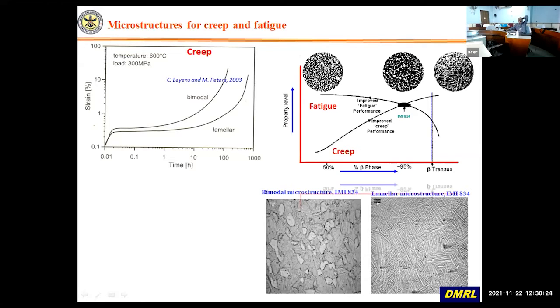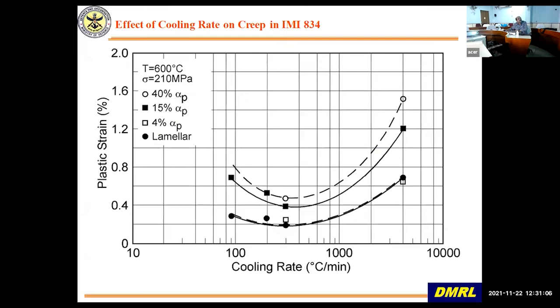Now, for applications like blades and all, where you have higher temperature and also rotating, you have to have a good combination of creep and fatigue. So that is why a bimodal microstructure is a compromise. You have optimized the bimodal microstructure basically to have good optimum amounts of creep and fatigue. So this is a beta treated lamellar structure, and this is a bimodal structure. The bimodal structure is what is used for compressor sections, for making blades and other rings, etc. Okay, so here I'm showing you why you want a bimodal kind of microstructure.